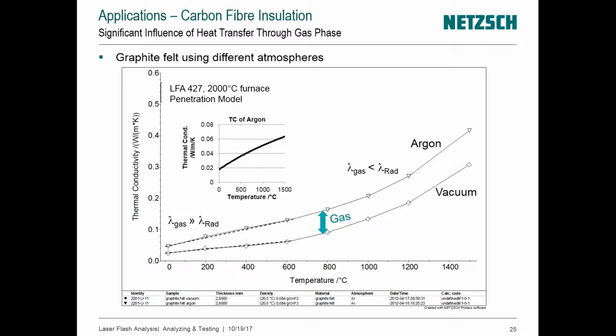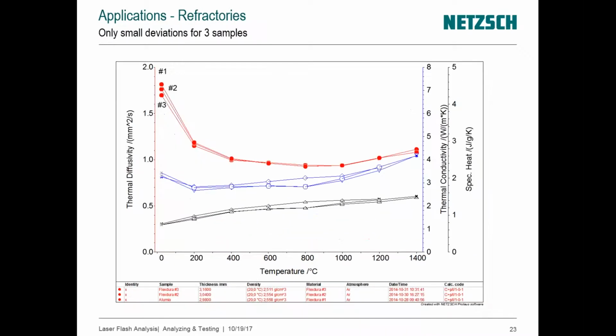And that's essentially what we are documenting, meaning that we can discriminate between conduction due to the material only, and conduction due to a mixture of the matrix, meaning the material, and the contributing gases, the gases filling the voids, in that case, of that graphite felt. This gives us confidence that even for a sample that is far less porous, meaning the bricks I referred to before, we are still able to measure it properly.